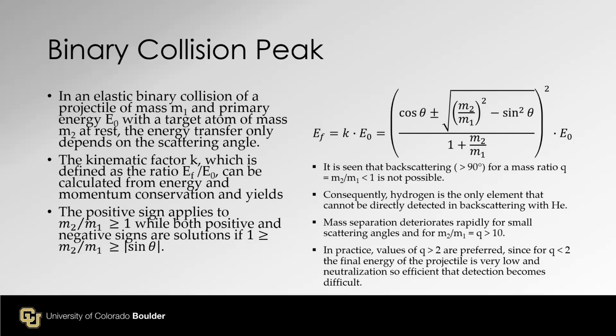the ratio between the primary ion and surface atom. Okay. Is this why you can't determine something like an oxidation state in LEIS, because it's just the atom? Yes. And not surrounding atoms? Yes. So we are not detecting electron energies, right? We are still detecting that same noble gas ion, but the energy would be different after the collision. Right, with that single atom. With a single atom, yep.